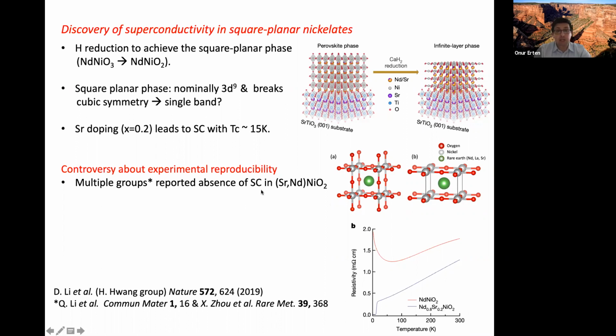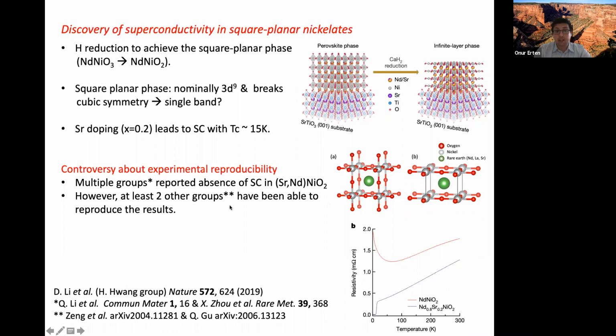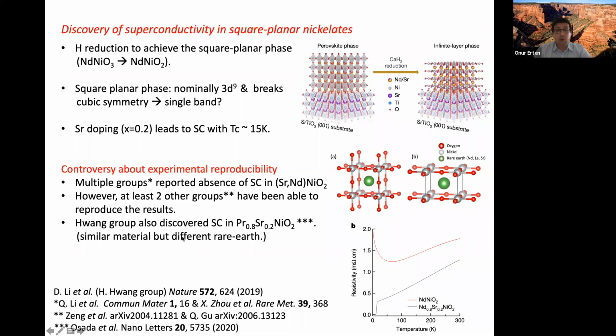At the same time, there are at least 2 other groups that have been able to reproduce these results in these papers. Okay, so these are not samples sent by Harold Hwang's group. These are other groups not connected to the Stanford group that were able to reproduce these results. And Hwang's group were also able to discover superconductivity in a related compound where the rare earth is not neodymium but praseodymium. It's practically the same compound because the rare earth does not play much of a role.